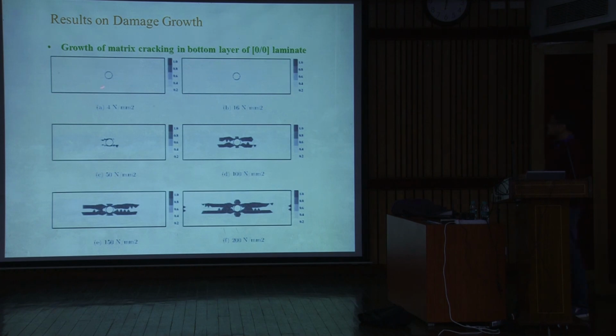So in this case, the matrix cracking can also take place, and again, as you can see here, it starts in the region where you have the stress concentration. As you know, if you are applying the load along this direction, then you will have more stress concentration here and here. So in this case, this matrix cracking takes place here, and it grows like this. As you can see here, it is along the length of the fiber. Okay, so this is the preferred direction of this matrix cracking.